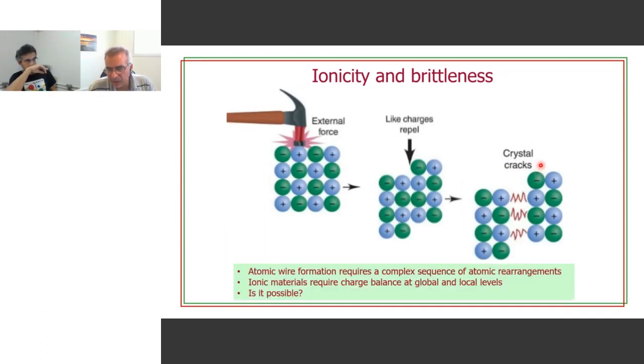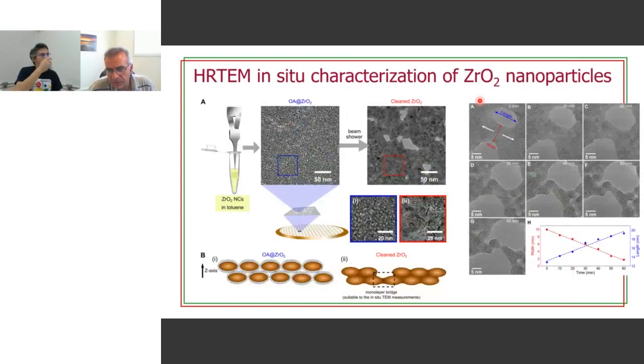So again, this is a cartoon, but if I want to say in words what this cartoon means, this is what I would say. Atomic wire formation requires a very complex sequence of atomic rearrangements, and this is very hard to be compatible with the fact that ionic materials require charge balance at global and local levels. So it would be very hard to envision a sequence of atomic rearrangements that in the end leads to the formation of an ionic wire. In general, you expect that materials that form wires are not brittle, right? So let's see what happens if one tries to do that.